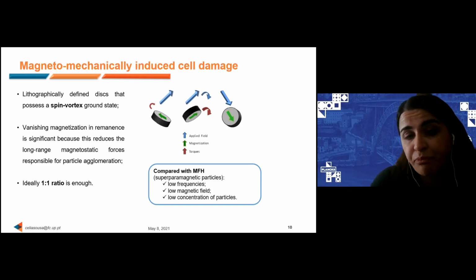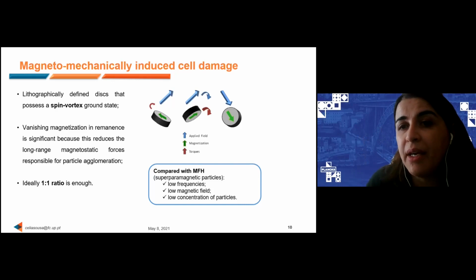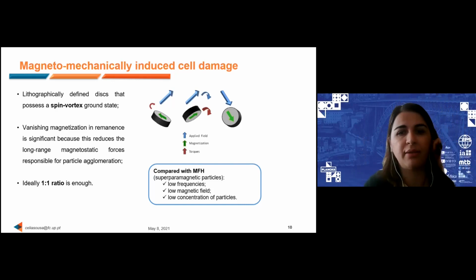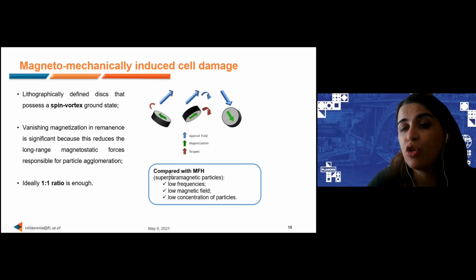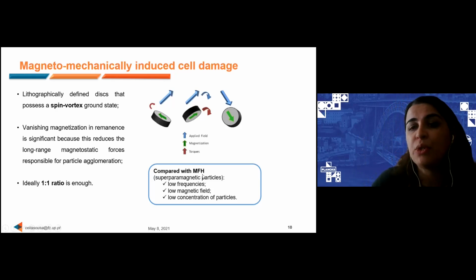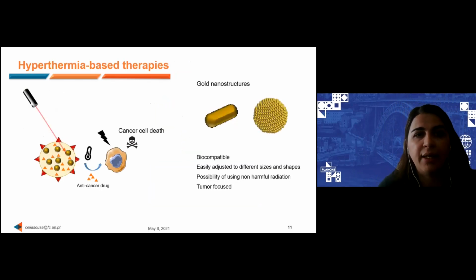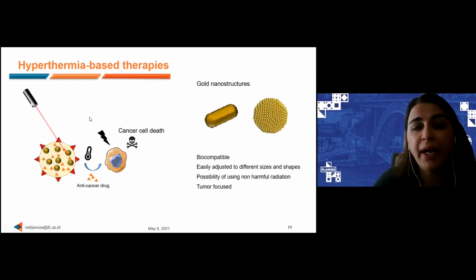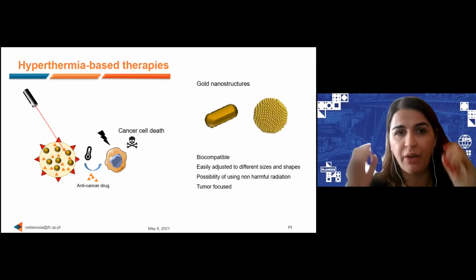In principle, one disc per cell will be enough to induce the cell death. So compared with the superparamagnetic nanoparticles used in magnetic fluid hyperthermia, we can perform a treatment with low frequencies, low magnetic fields, and very low concentrations when compared with the state-of-the-art techniques. On the other hand, we can use the plasmonic nanoparticles for plasmonic hyperthermia or phototherapy.